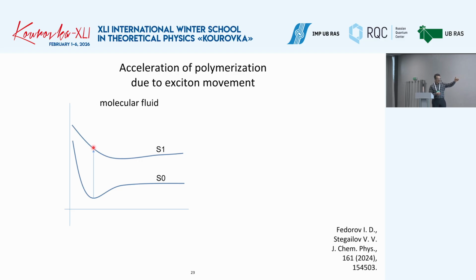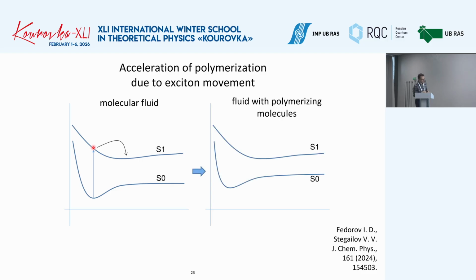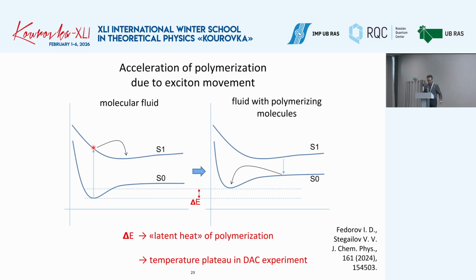Some exciton forms when kinetic energy of atoms goes into electronic excitation. Then it evolves for several femtoseconds, maybe hundreds of femtoseconds. The positions of atoms rearrange, the covalent bonds rearrange, and then it recombines. But our fluid is in another, polymerized state. And there is some difference in internal energy after this one exciton made something with our system. And this is the energy that is detected in the experiments as the observed latent heat of such a phase transition, so to say.